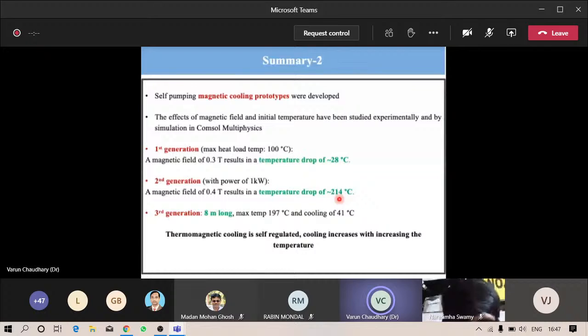Third generation, on which we are working on, we prepared a device 8-meter long, where we fixed the maximum temperature 197, and we achieved a cooling of 41 degrees centigrade. So the thermomagnetic cooling is self-regulated, and cooling increases with increasing the temperature.